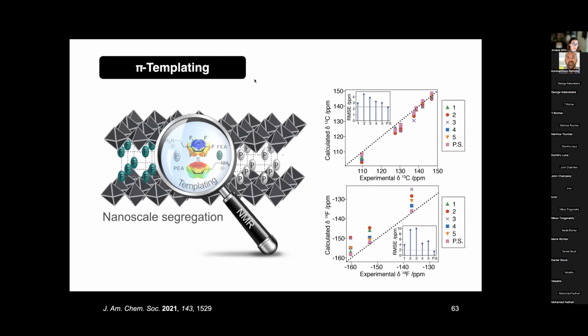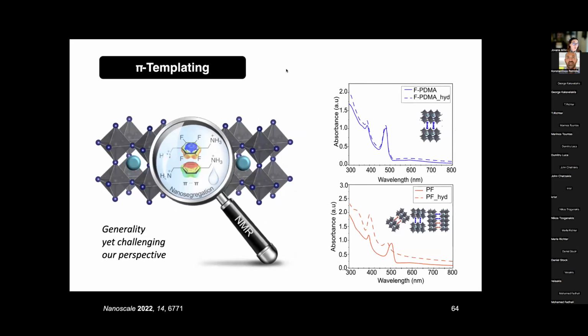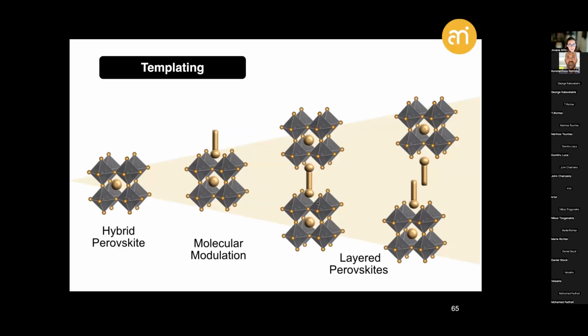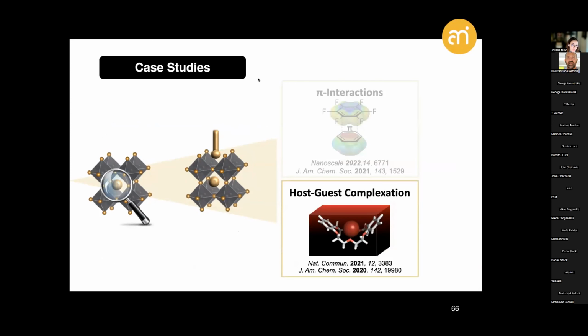Importantly, this effect is also general in the sense that we observe the same behavior when moving from Ruddlesden-Popper to the Dion-Jacobson architectures, where we see comparable nanosegregation occurring with these materials that further affects their affinity to hydration, for example. That is important, and it really challenges our perspective on the role of pi templating in advanced material design. Now, this is relevant for these layered perovskite architectures, but equally important when considering these other approaches that are more interfacial, molecularly modulated treatments, which I would like to briefly come back to in my last example that involves the role of host-guest complexation.